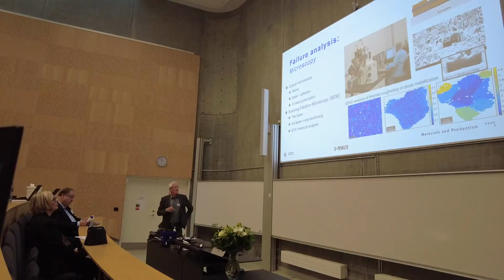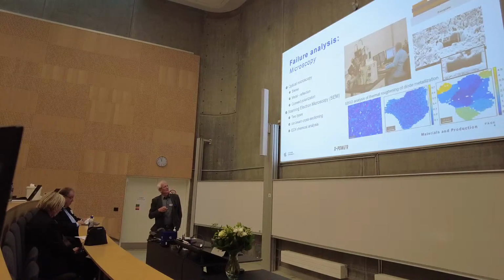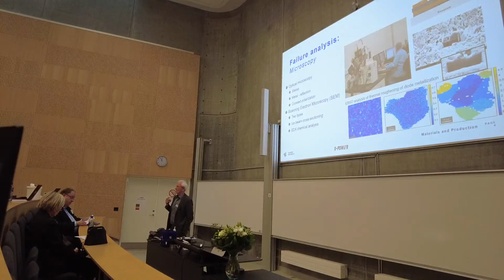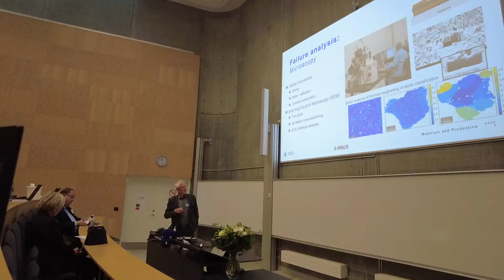This here is an example of using electrons scattered backwards in the microscope. We've been looking at the diode of an IGBT and realized that just thermal cycling of the diode created a very rough surface over time. So as we kept on cycling it, the surface got more and more rough. And we then started to look at that. This is an image of the grains that you can see. Then we focused down to one grain.